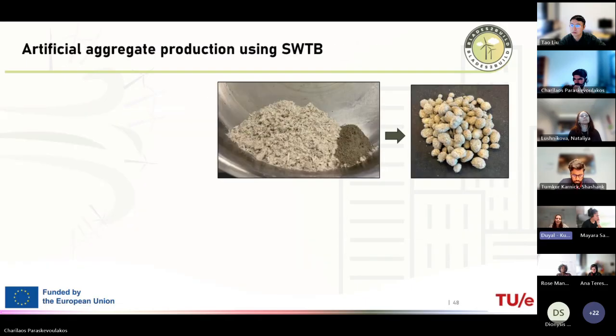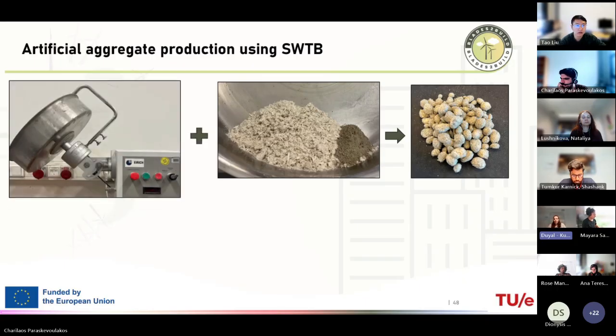If you can go to the next slide. So if we can create granular materials which are repeatable and more aggregate-like particles from this very heterogeneous waste, then we can solve so many problems caused by the heterogeneity of the material. If you continue, the way to do it, there are several methods to create artificial aggregates, but the lower energy consumption method is cold bonding pelletization. What is this?